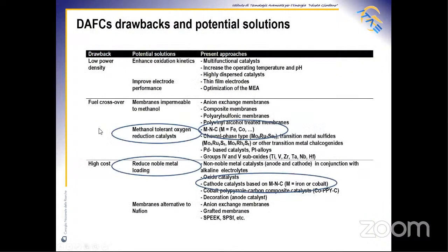The factors contrasting a large-scale commercialization concern sluggish kinetics of the electrochemical reactions and the consequent high cost, more than 50% derived from the use of noble metal catalyst. Furthermore, direct methanol fuel cell systems able to work with high fuel concentration would mean a significant step forward towards high capacity electrical systems. Unfortunately, the higher the alcohol concentration, the worse the influence of permeated methanol on performance due to the crossover effect.